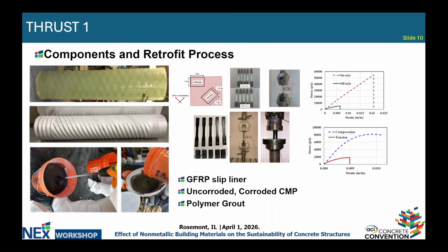So talking about thrust one, which is that flexural response that we were studying, and this is primarily Dr. Channareddy's dissertation. We see a GFRP slip liner system here, and the bottom picture is of a corrugated metal pipe. Basically, you have the slip liner going into the corrugated metal pipe. Each of these materials were evaluated for their own properties and mechanical performance. There on the bottom, you have the grout. A polymeric grout, two-component, was used for this particular project,